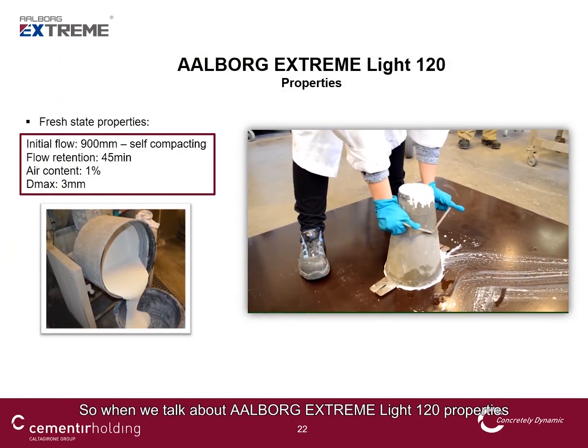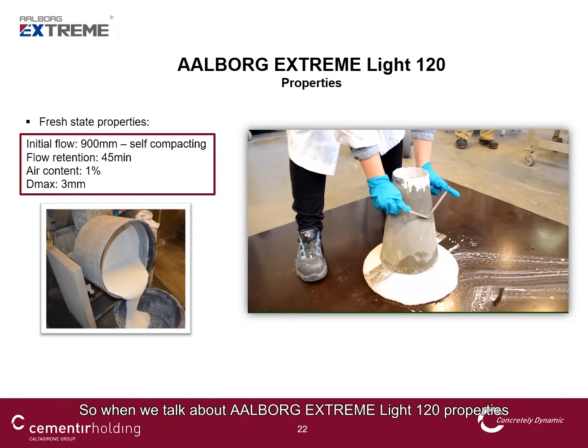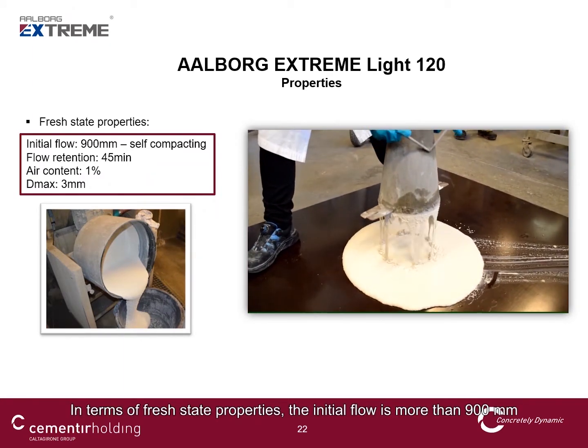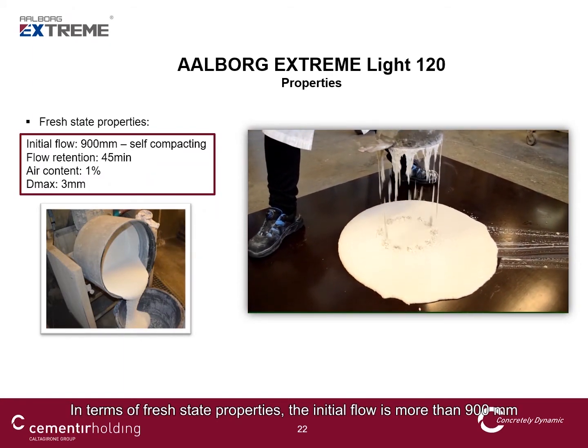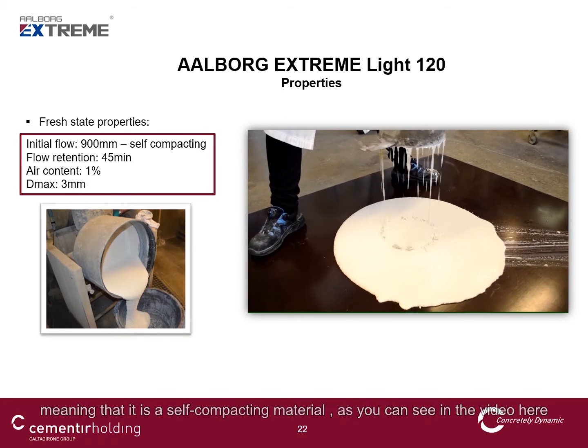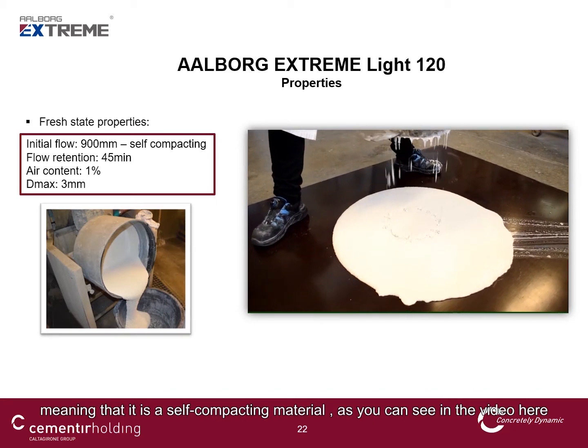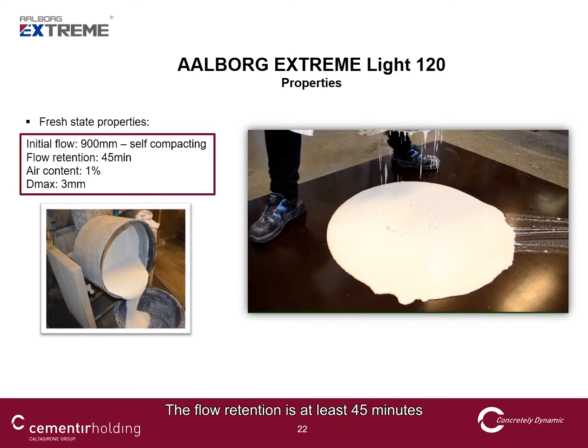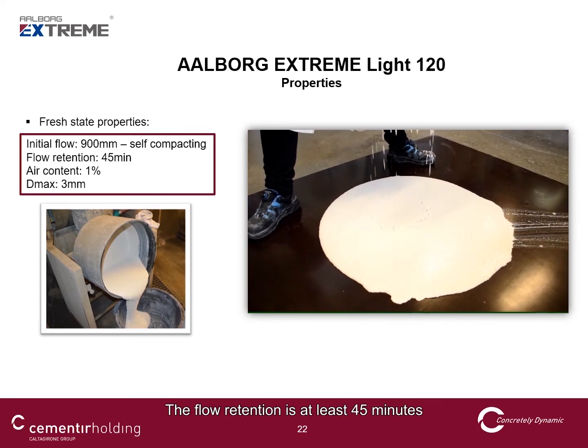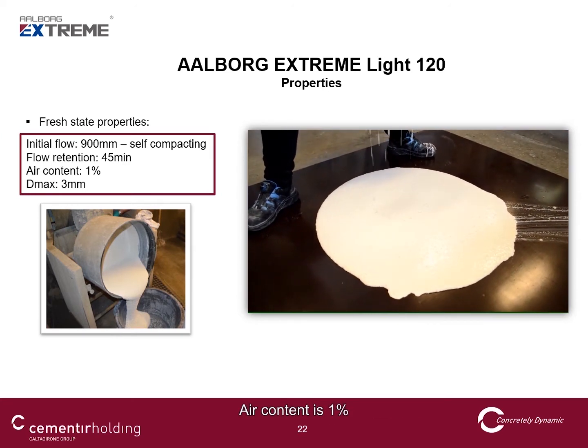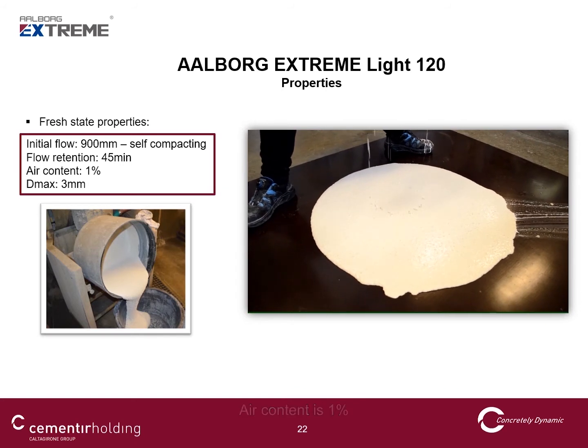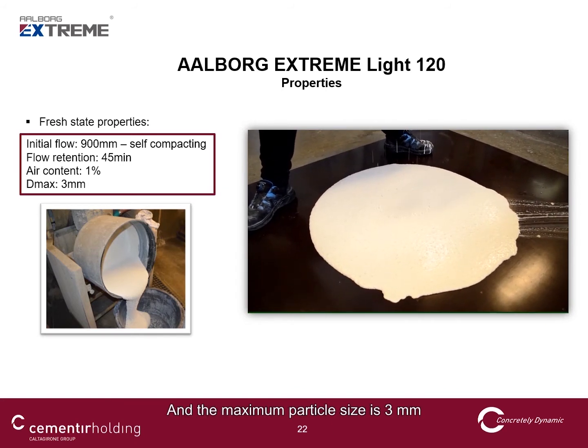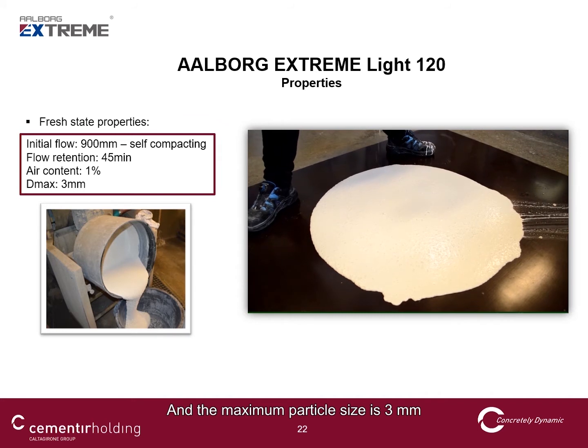So when we talk about AALBORG Extreme Light 120 properties, in terms of fresh state properties, the initial flow is more than 900 millimeters, meaning that it's a self-compacting material, as you can see in the video here. The flow retention is at least 45 minutes. Air content is 1%, and the maximum particle size is 3 millimeters.